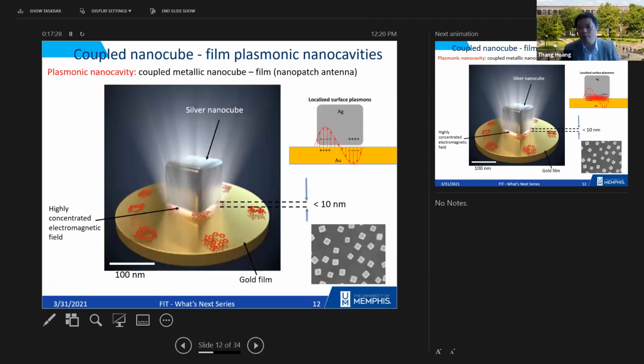Let me show you one example. In this example, we have a nanocube, for example made of silver, and we put it on top of a gold film, as you see here. And like before, underneath this nanocube, between the nanocube and the gold film, the electromagnetic field is going to oscillate. The charge is going to oscillate up and down, like what I drew in the cartoon on the top right here.